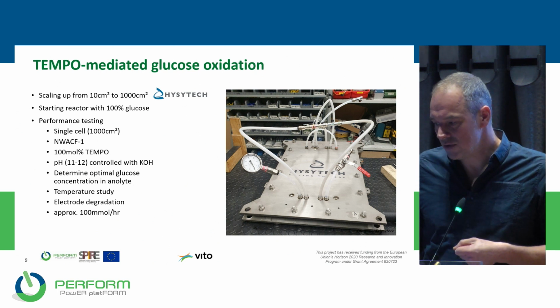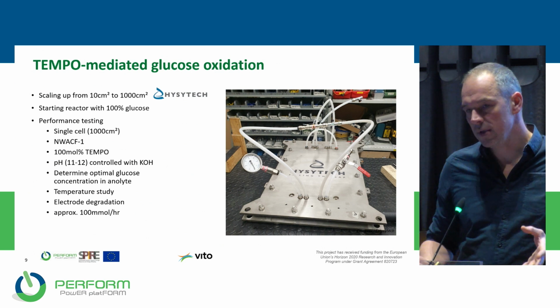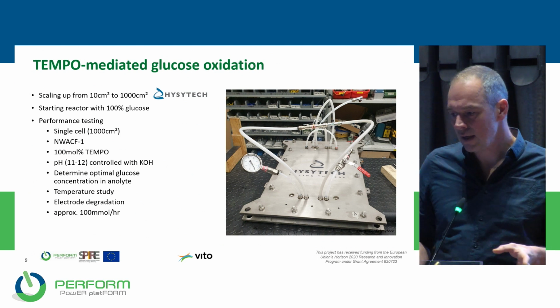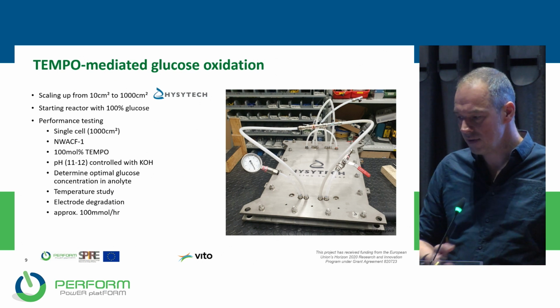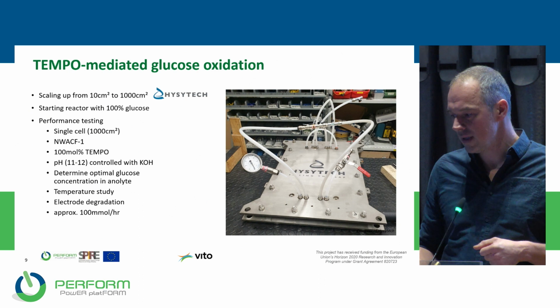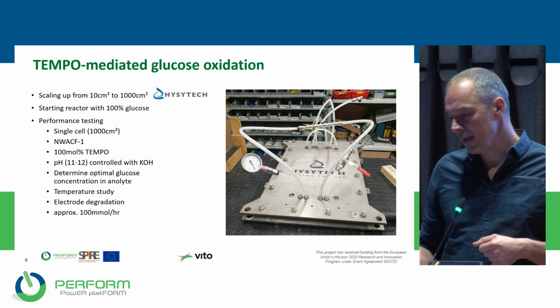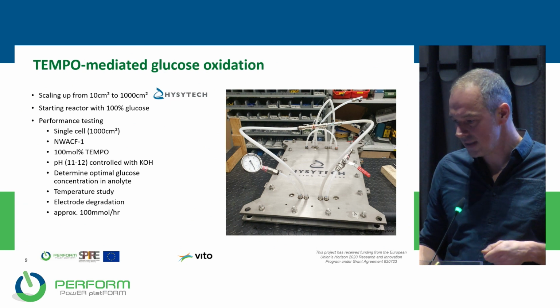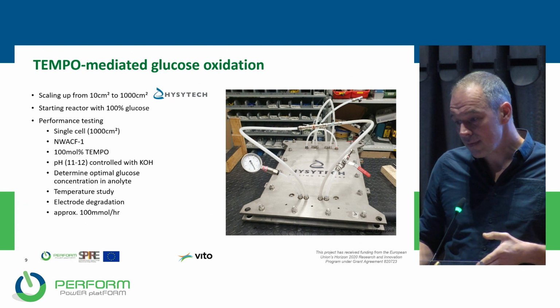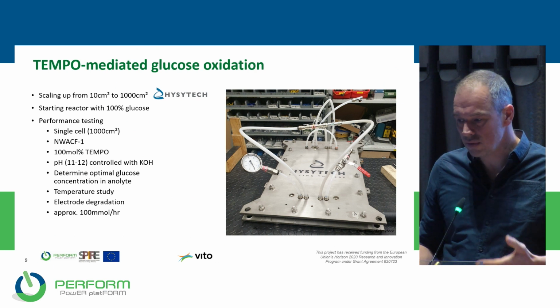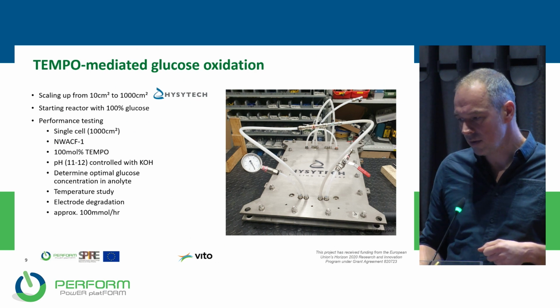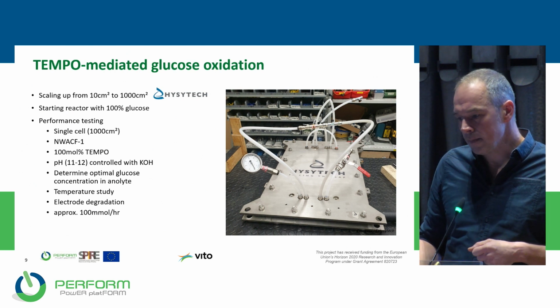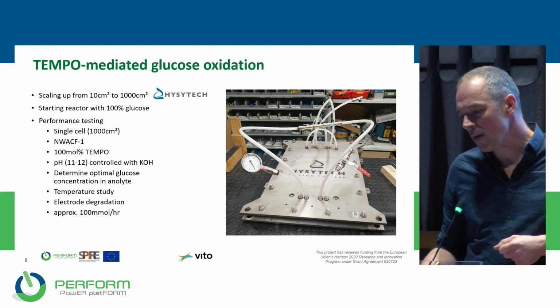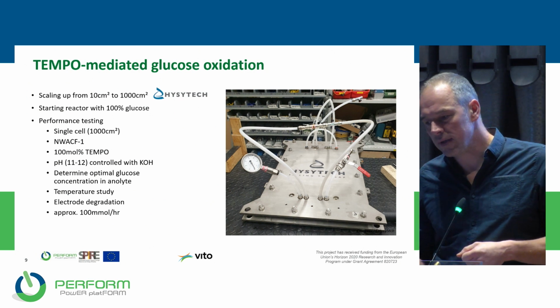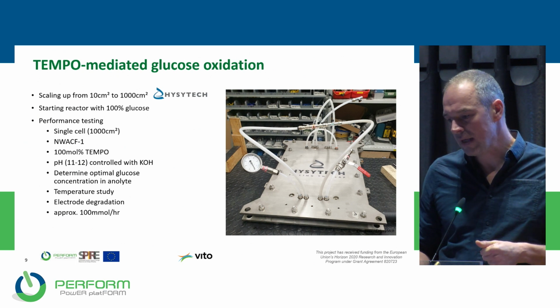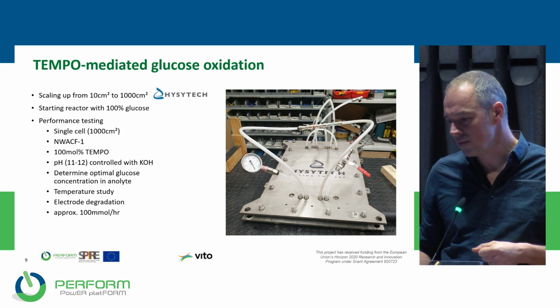This then led to the following step, so the scaling up, which was one of the main goals in Perform, scaling up from 10 square centimeters in the microflow cells to 1,000 square centimeters. You can see the stack here. This is actually a single cell, which was designed by HYSYTECH, and where we started to run tests with the mediated glucose oxidation reaction. So we performed tests with 100 mole% of TEMPO at pHs around 11 to 12, and we followed the electrode degradation.